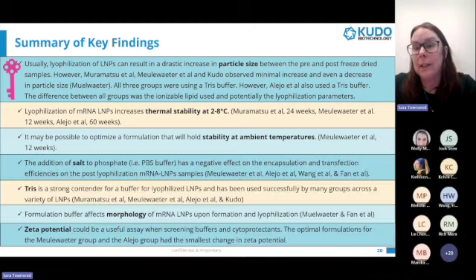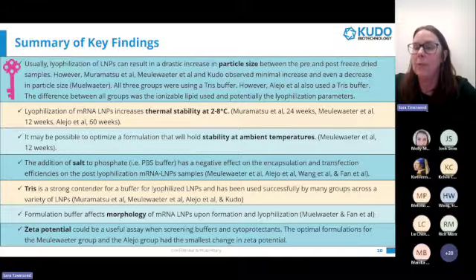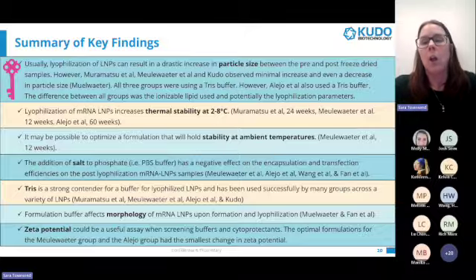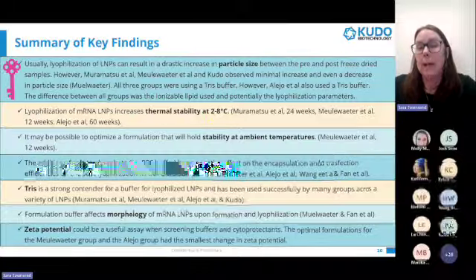Summary findings. A review of several journals on lyophilization of mRNA-LNPs revealed some interesting things. One, it is possible to lyophilize particles without obscene particle size growth. Two, lyophilization is a strong pathway to removing the need for our ultra-cold chain. Three, salt-based buffers should be avoided. Tris at any concentration is a strong contender for a buffer for LNPs, but more buffers should be investigated. TEM and zeta potential tell us about the structure of the LNPs in various situations and before and after lyophilization. The final key to understanding thermal LNPs lies within the internal structure of the LNPs.